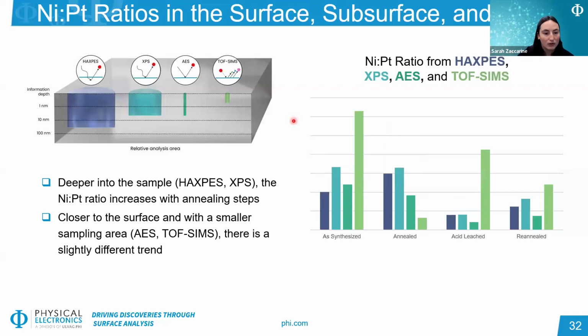When we compare this with Auger data, which is in the dark green, so this is moving slightly more surface sensitive, we see a trend similar to XPS where the as-synthesized and annealed samples are slightly similar. We have a decrease in this ratio with acid leaching, and then it increases slightly again after re-annealing. With TOF-SIMS, which is the most surface sensitive, we see a slightly different trend. So this is suggesting between these different techniques that we have a different composition in the nickel and platinum amounts in chemistry at the very surface and the subsurface, and then further down towards the bulk of the material.